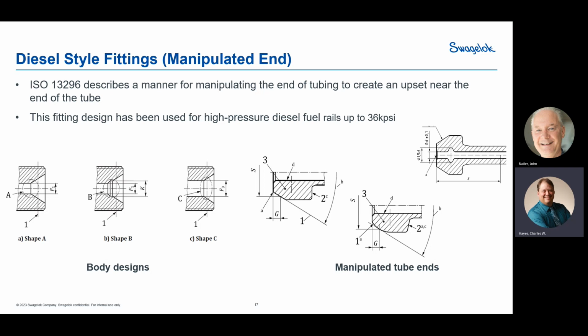So it's got a hard end on one side and then a tube adapter or something else on the other side to be able to allow you to connect close couple fittings with a very, very short moment arm between the two. What we know about them is that they have a tendency to crack when you're in high cyclic loads. So things like at the end of a compressor where it's seeing a lot of vibration, what'll happen is they'll crack right here. They'll crack at the neck.